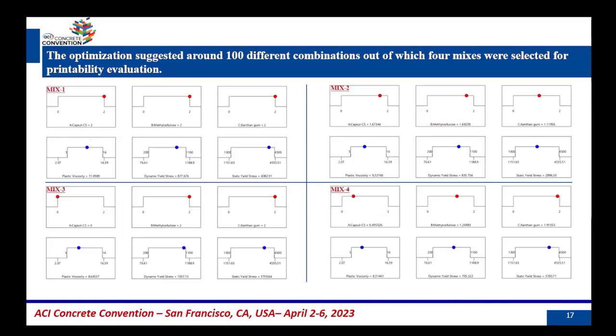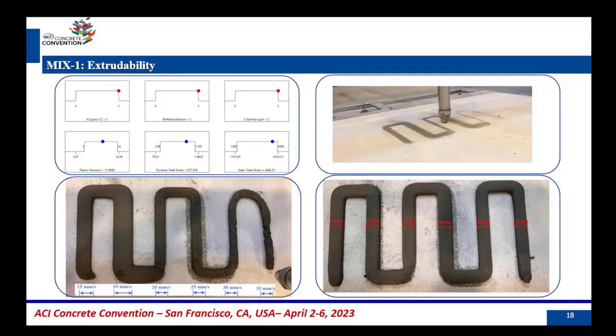graph too. Okay, so after optimization through response surface methodology, the optimization suggests around 100 different optimized mixes. We selected 4 different mixes for preliminary printability evaluation based on the values of static yield stress, plastic viscosity, and dynamic yield stress. So the first mix contained 2% of all 3 factors A, B, and C.